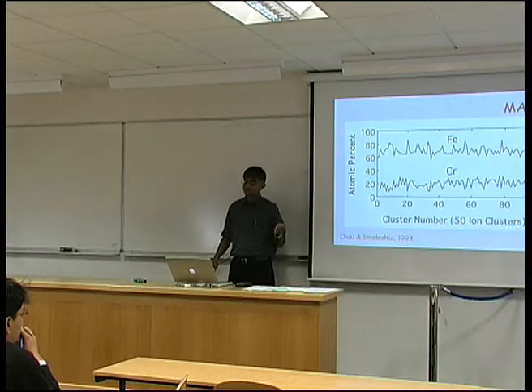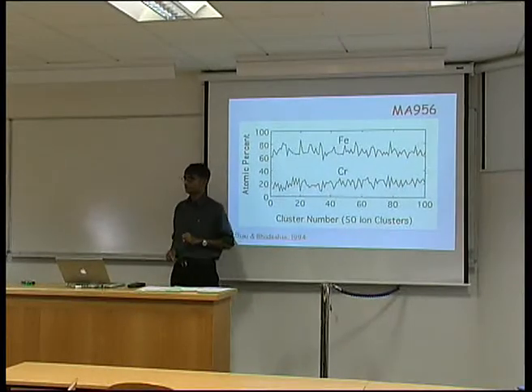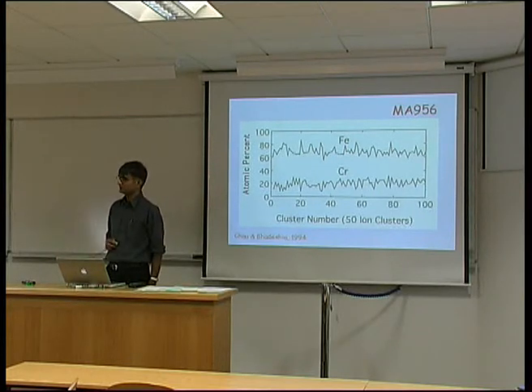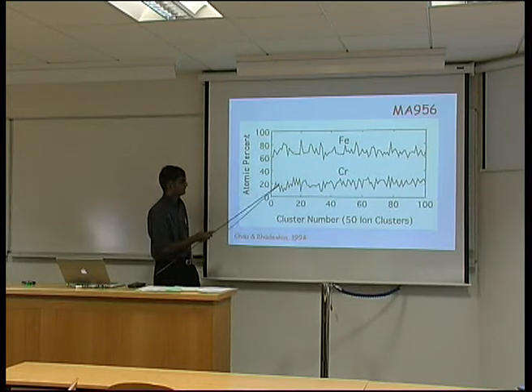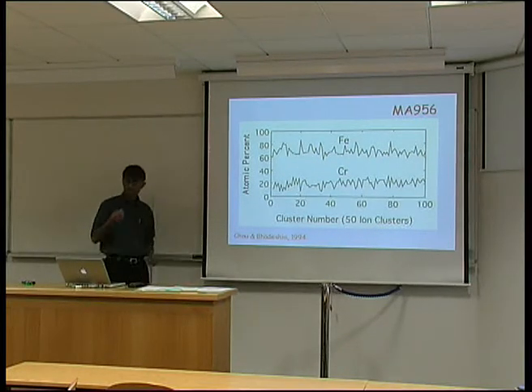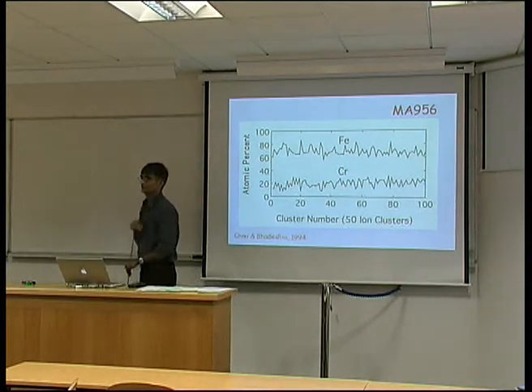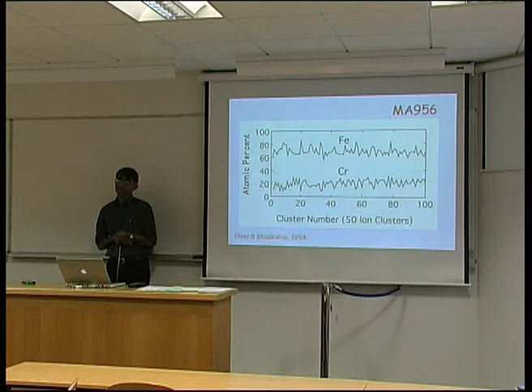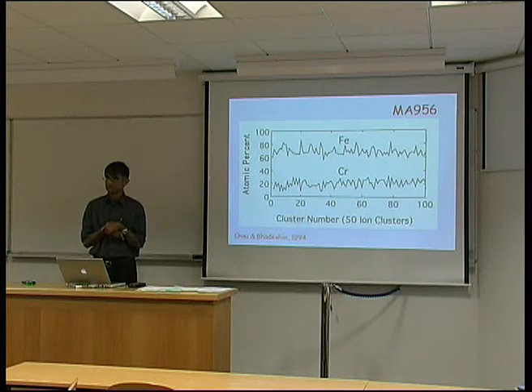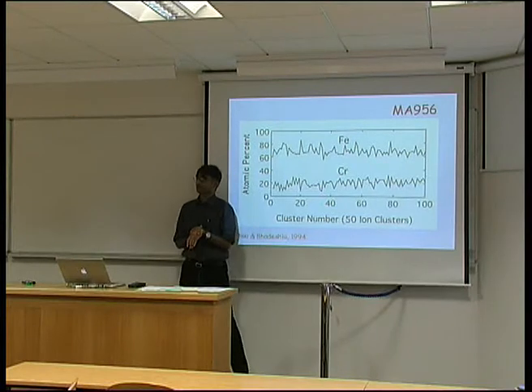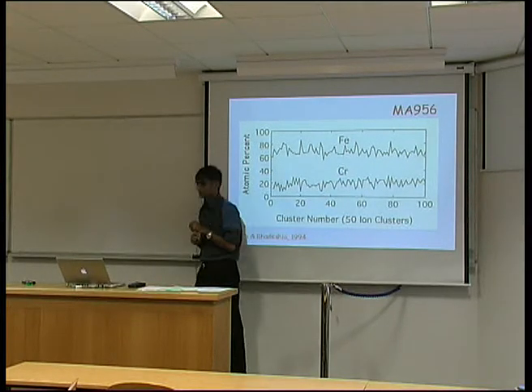You get both spatial resolution which is atomic and chemical information which is atomic. To determine whether this is a solid solution, all I need to do is pull out a stream of atoms, measure their chemical compositions, and see if I get large clusters of chromium and iron instead of a nice mixture in the sequence. Here is such a sequence, plotted in groups of 50 ions. If I plotted just one at a time, I would have 100% chromium, then 100% iron — not very informative. Each point here is an average value over 50 ions. The question is: is this a solid solution? Is this homogeneous? I can observe variation from 60 to 80% iron — should that worry me?